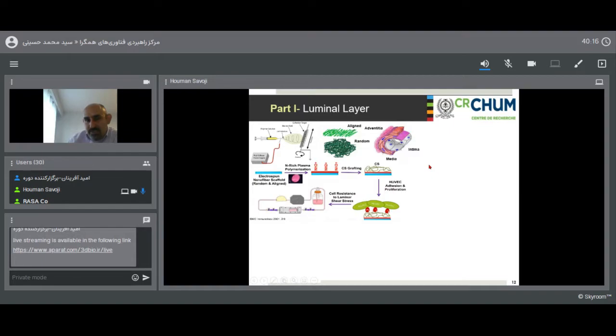So with electrospinning, I don't think that I need to explain electrospinning, but this is the technology that was rediscovered from the textile industry to make fibers. And the technique is very simple. You put the polymer solution inside the syringe, and then by adjusting the parameters like the voltage, the distance from the needle to the mandrel, the mandrel speed, the polymer flow rate, and the viscosity or rheology of the polymer, you can have different fibers like aligned fibers or random fibers with different structure and porosity.